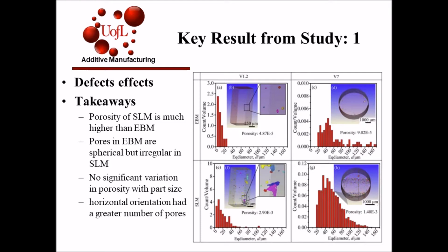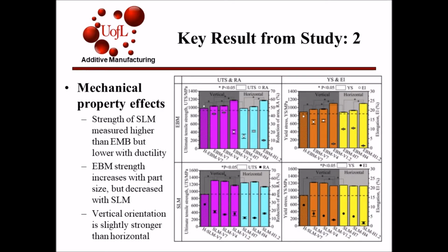No significant variation in porosity was found for differing part size, but porosity in SLM samples was much higher than the porosity in EBM samples. Also, not shown in the graph, but another observation was that the horizontal orientation had a greater number of pores than the vertical orientation. Key results for mechanical properties.